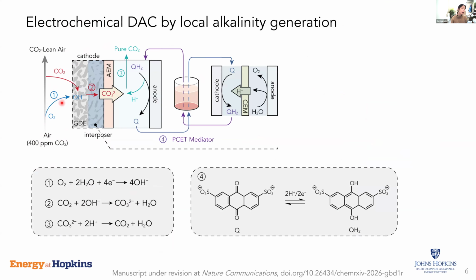So basically, we're using the abundant oxygen in the air as a source to in situ create hydroxides through the oxygen reduction reaction. So oxygen gets reduced to form hydroxide, so that we can generate a very high concentration of hydroxide at the local gas-liquid interface. And that very high local alkalinity can promote the rapid reaction between this hydroxide and carbon dioxide from air to achieve carbon capture. And then later, after the reaction, this carbonate species will get transported across an anionic selective membrane and get regenerated to release pure CO2 at the anode side of the reactor.